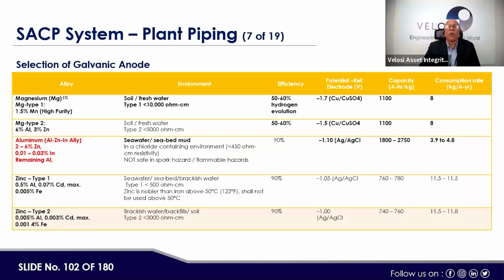Then the selection of the galvanic anodes. Here, what type of anode we'll be using and in what kind of environment, then their efficiency factor, the potential reference of electrodes, then capacity in hours. It will help to assume the consumption rate or age. The best one, as you can see here, is zinc, with 90% efficiency, the Ag/AgCl potential, and capacity of 740 to 760. The bigger one is aluminum, 1800 to 2750, with consumption rate 3.9 to 4.8. This way we have to select what type of anode we want to use.